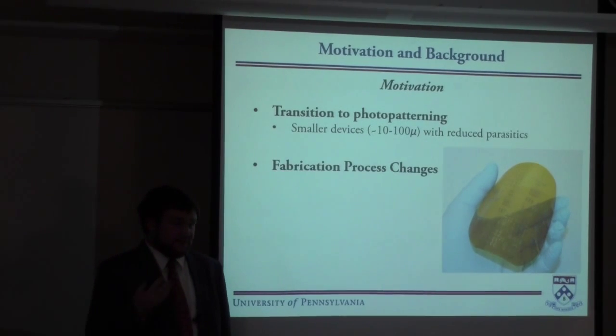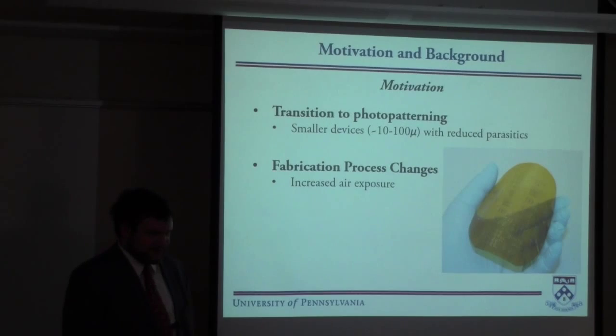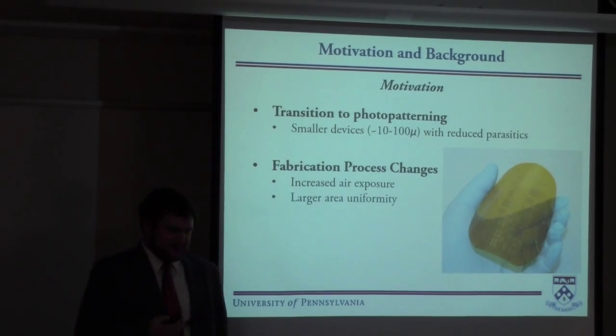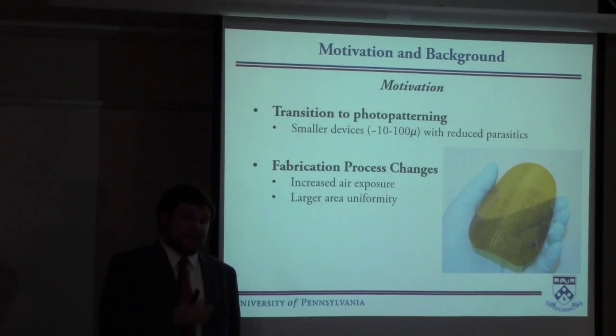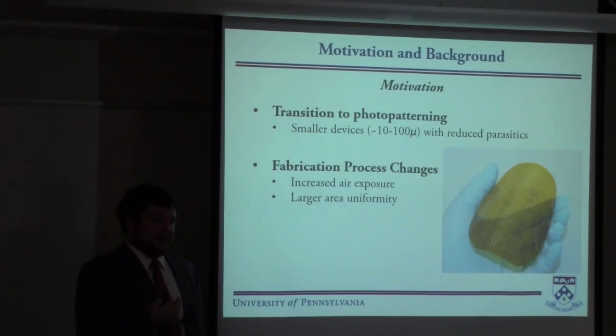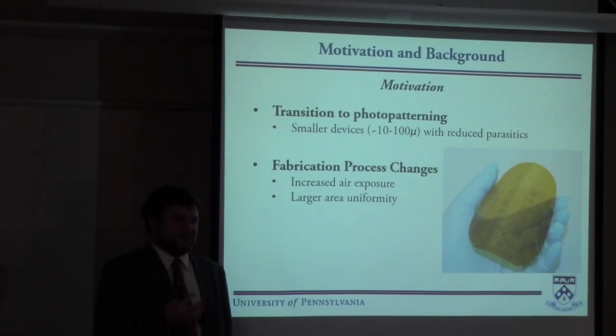But that introduces some problems, like some fabrication process changes. So increased air exposure and larger area uniformity are concerns, because these cadmium selenide nanocrystals have a very high surface area to volume ratio, which makes them very, very oxygen sensitive.